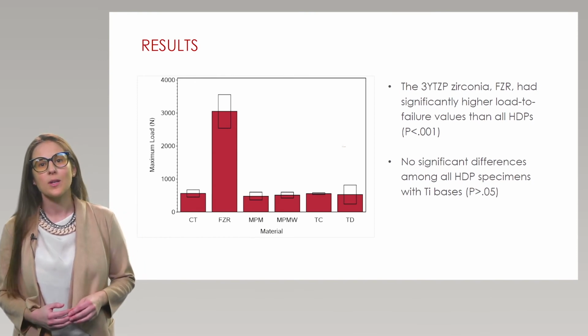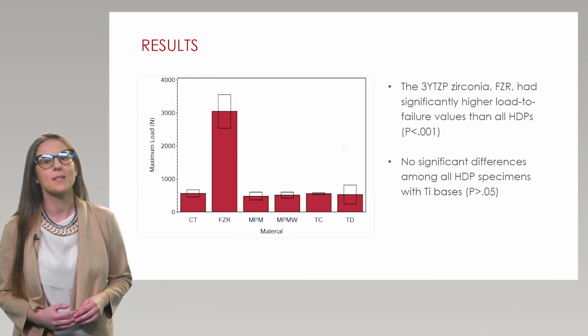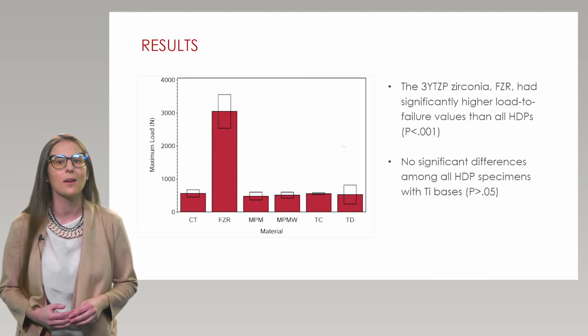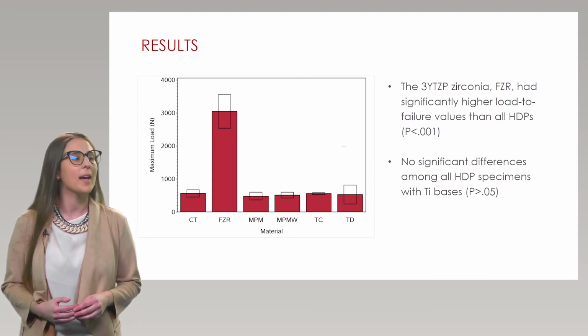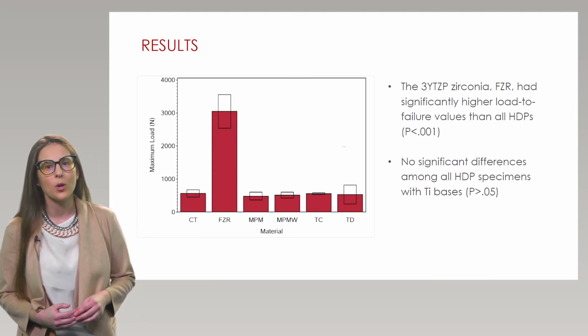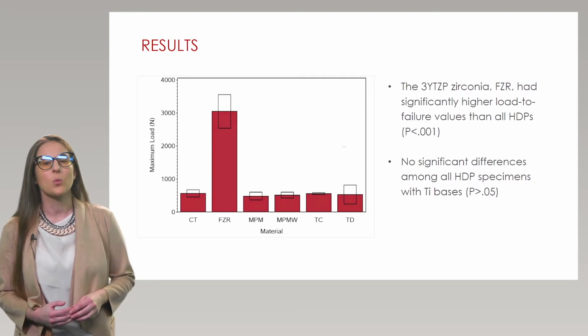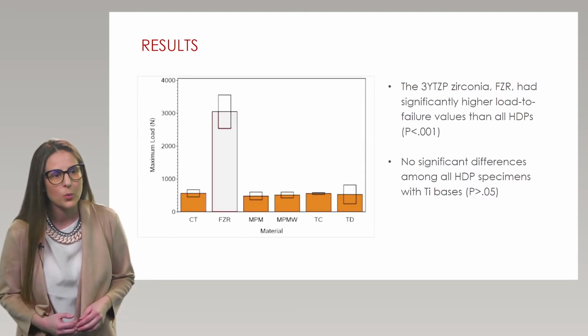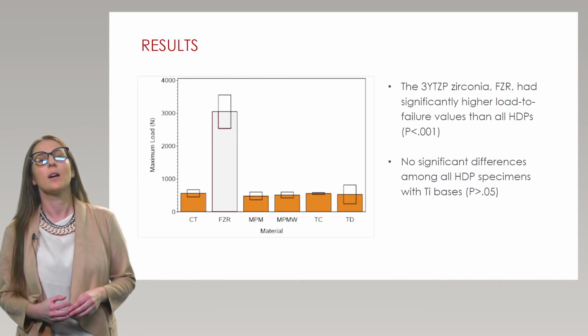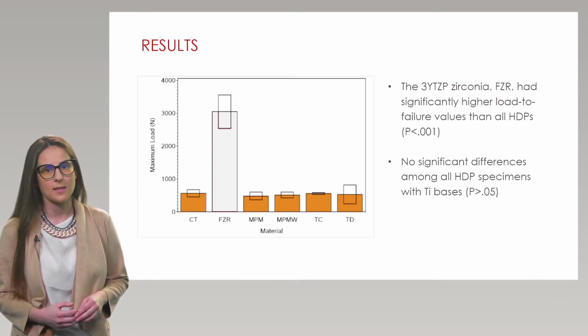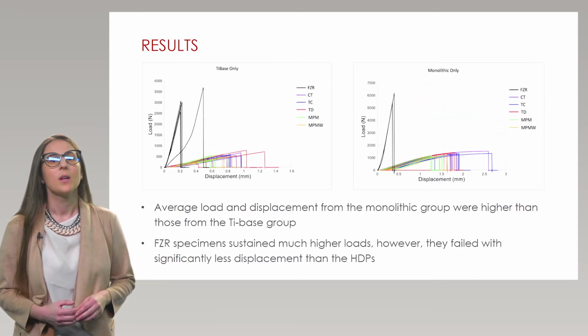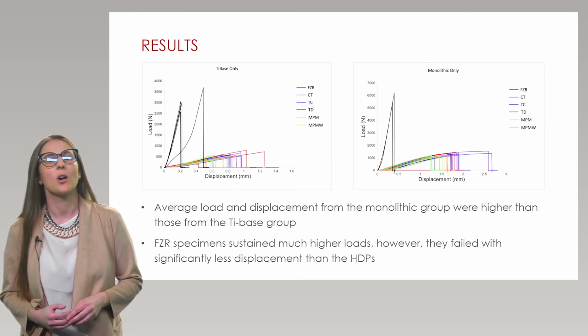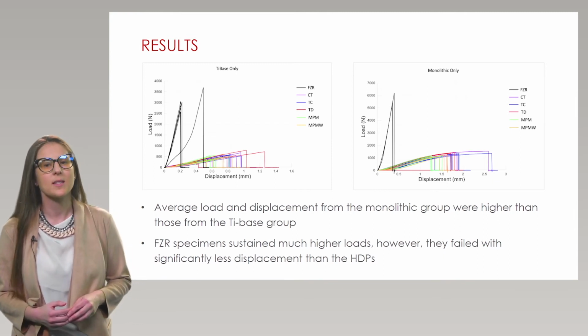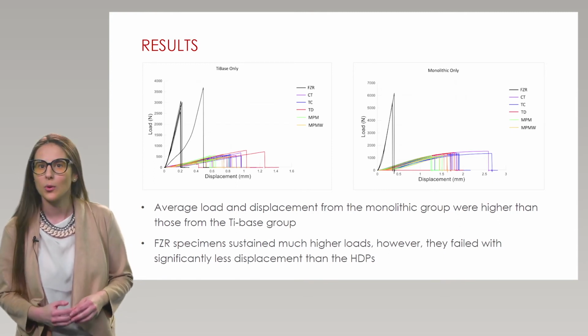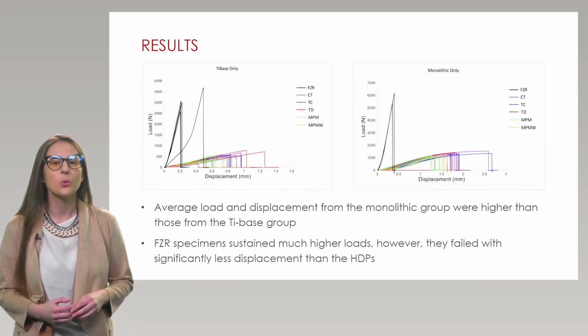Sure. As it emerged from the graph, zirconia sample with T-bases presented a significantly higher load to failure values than the high performance polymer sample with T-bases, while no significant differences were observed among all high-density polymers with T-bases. Load displacement curves of high-density polymers and zirconia with T-bases and in monolithics are presented in 2 graphs.